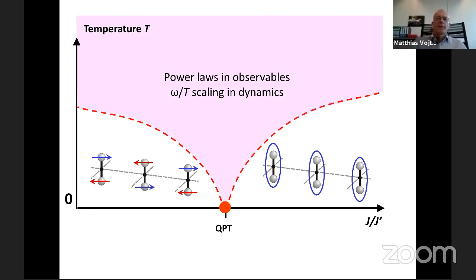That's a good question, and partial work has been done. One has to keep in mind that the work on spin liquids comes from 2 branches. One is people try to construct exactly solvable models, or almost exactly solvable models, which can be solved in a controlled fashion for particular spin liquids. And a few of them exist by now. The other is people do numerics for realistic Hamiltonians and try to figure out whether a spin liquid phase is realized somewhere in the phase diagram of a given model. The numerics becomes increasingly difficult with increasing spin because the Hilbert space gets larger, which means there are good results for spin 1/2 models, a few results for spin 1 models, and essentially no results for higher spin.